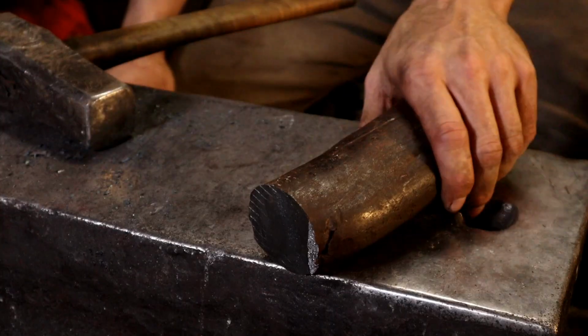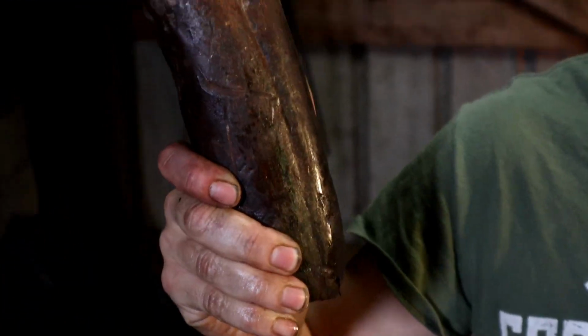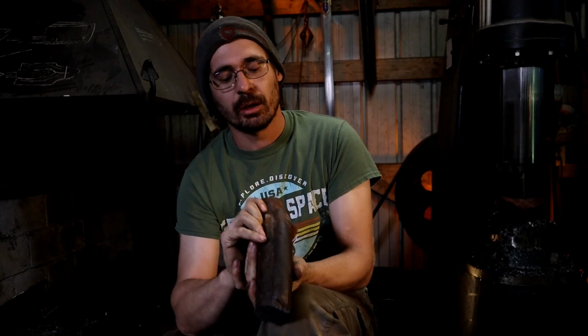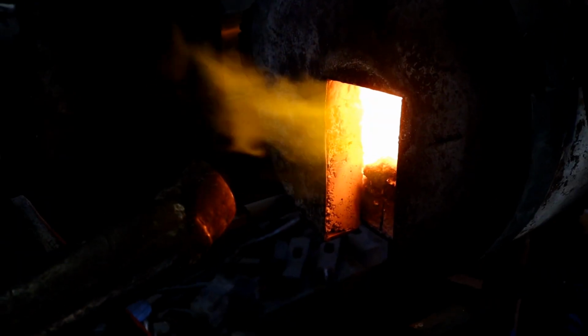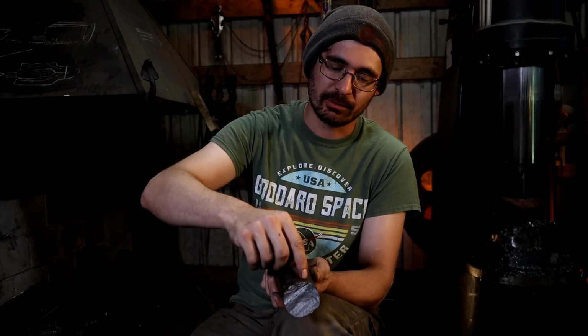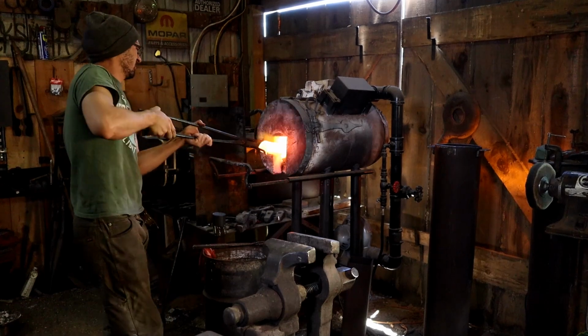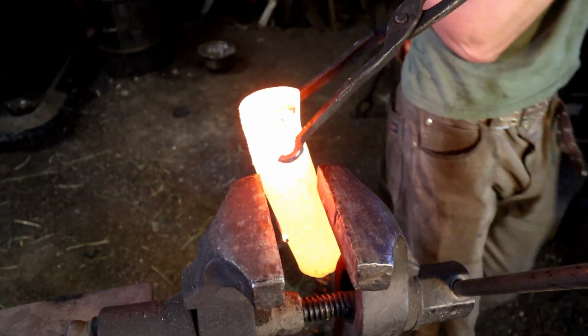Now that the chain has been cut, one thing to notice is these are always welded on anchor chains, and this is not usable material right here. It is actually stick welded to prevent erosion when the chain is pulled in and out from the ship. So before I do anything, I have to heat it up and use a hot cut to remove the entire thing in the vise. After that, I will square it up, cut it off, and size it.